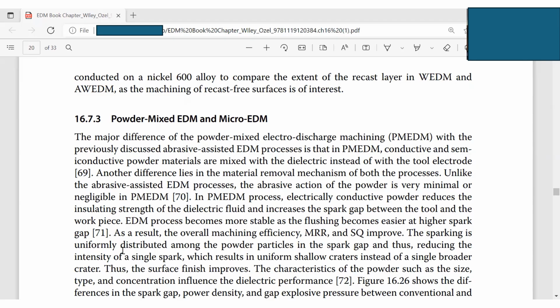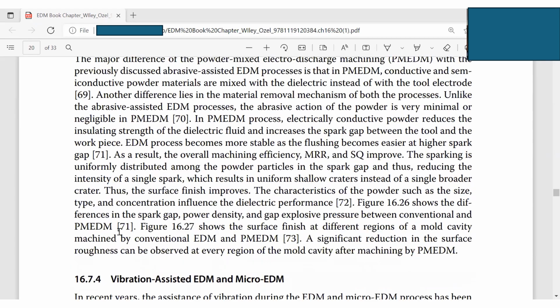So the spark is uniformly distributed along the powder particles in the spark gap, thus reducing the intensity of the single spark, which results in uniform shallow craters instead of single broader craters. So this is the effect, okay? And thus, the surface finish improves. So the characteristics of the powder, such as the size, powder type, and the concentration, influence the dielectric performance.